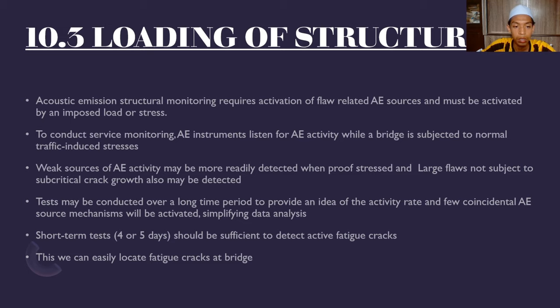Tests may be conducted over a long time period to provide an idea of the activity rate, and the fatigue crack AE source mechanism will be activated. This simplifies the data analysis. In short-term tests, four or five days should be sufficient to detect active fatigue cracks. Thus we can easily locate fatigue cracks on the bridge.